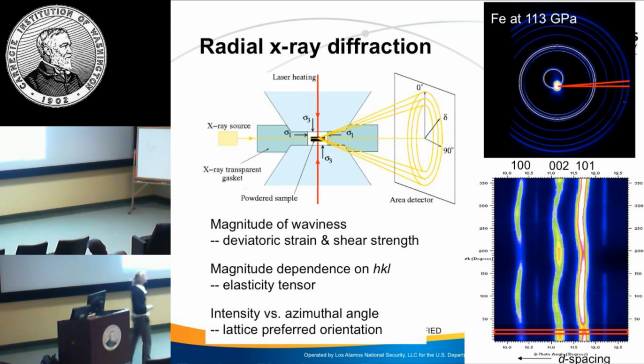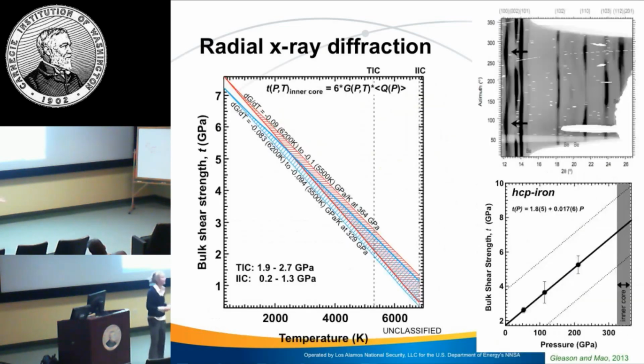So we executed this experiment in a diamond anvil cell to come up with a bound for the strength. And we found, not to go into too much detail, here's strength as a function of pressure, using something called a SING methodology, which has some underlying assumptions, but it's a rough bound, and we find that the strength is fairly low. Okay, it's like 8 GPa. This is at room temperature.